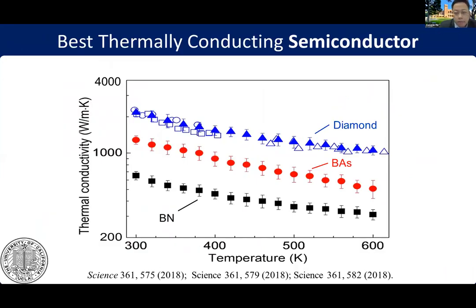So we made here the 3 prototype high thermal conductivity materials. And you can see that the thermal conductivity of boron arsenide is over twice that of cubic boron nitride and only exceeded by diamond. The high thermal conductivity of boron arsenide has also been verified by collaboration teams involving Gang and David and several other groups. So if you think about the general definition of common semiconductors, then boron arsenide is established as the best thermally conducting semiconductor. I emphasize here that being a semiconductor, it has advantages for integration with electronic devices, such as compatible properties in mechanics and thermal interfaces.